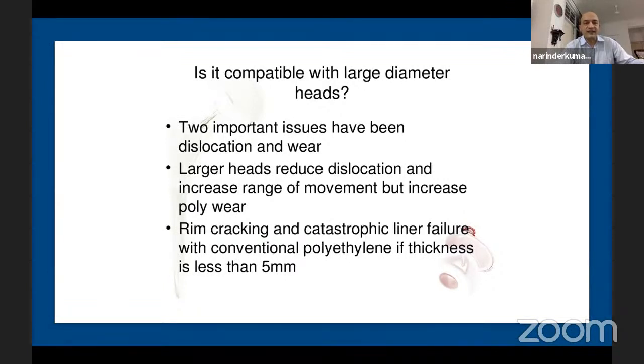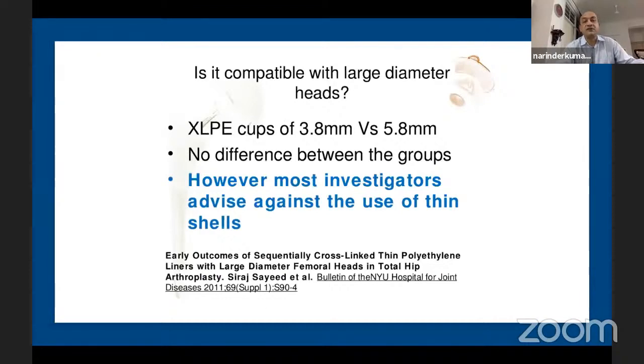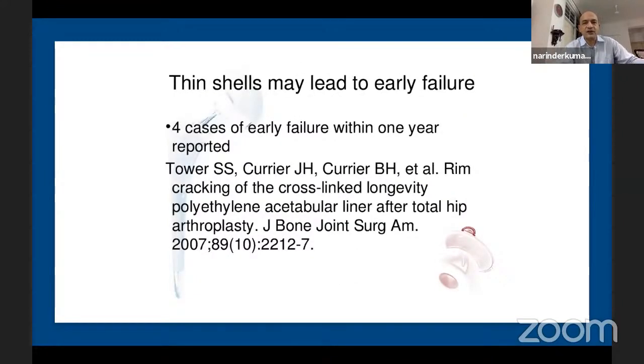But that comes at a cost of higher poly wear. So with fatigue setting in over a longer time, rim cracking and liner failure can happen with conventional poly as well as with cross-linked poly if thickness is less than 5 mm. There is a study comparing a 3.8 mm cross-linked poly with a 5.8 mm one that found no difference, but most investigators and surgeons would not like to use a liner thinner than 5 mm, since they can lead to early failure. There are cases which have been reported.